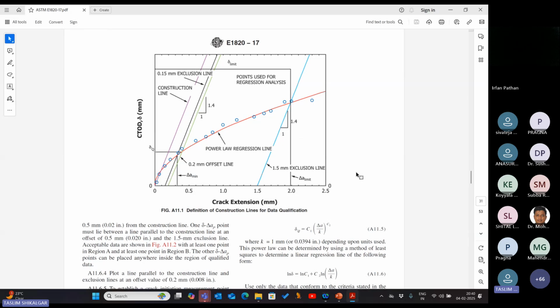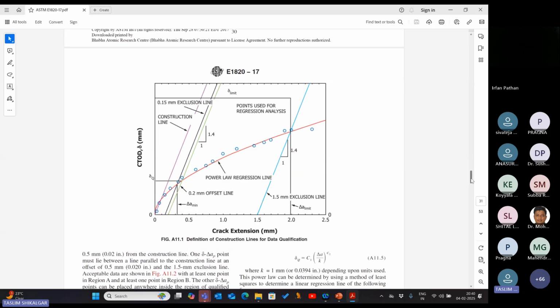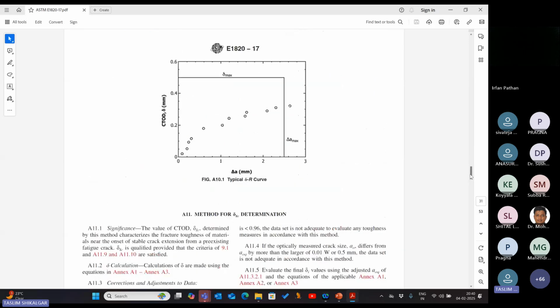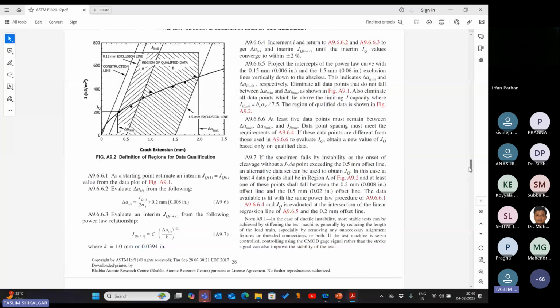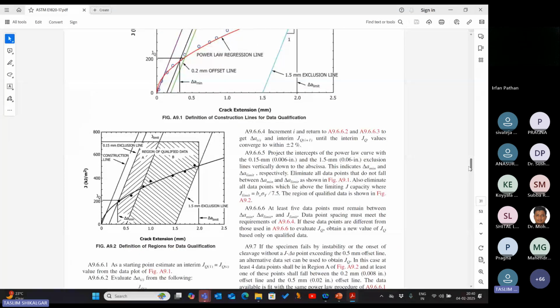So people, similarly here you can see the CTOD versus crack extension. They generated similar curves, but they used some correlations because ASTM is not directly proposing a way to calculate the CTOD. They are proposing to perform the J integral approach only.